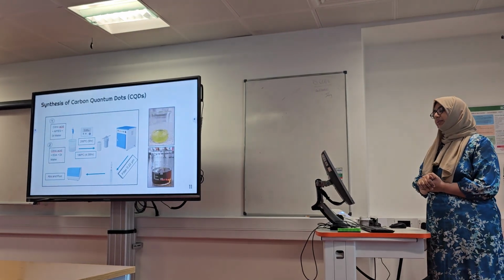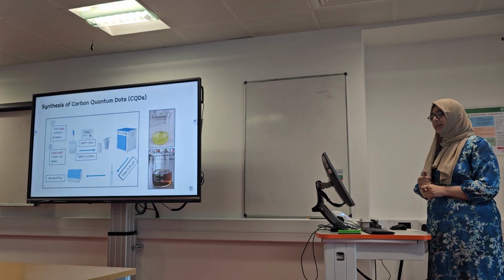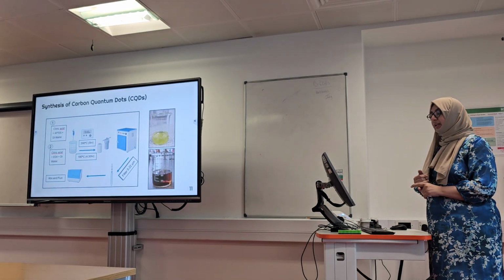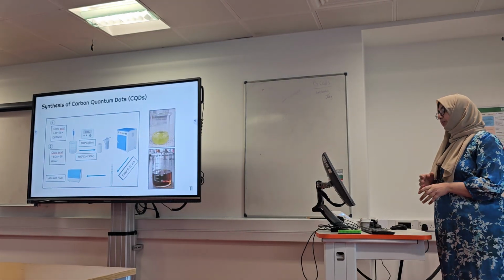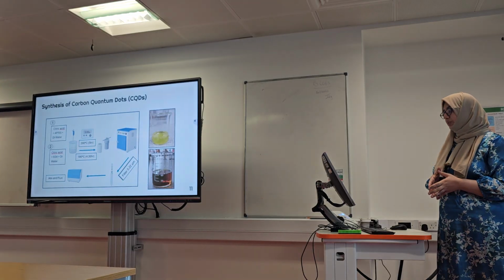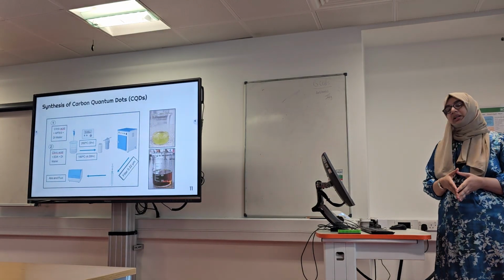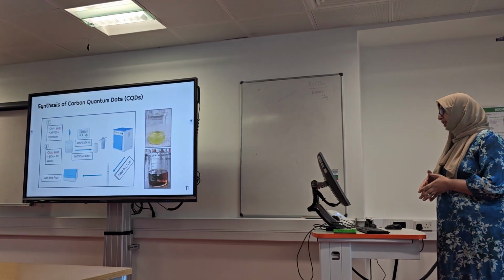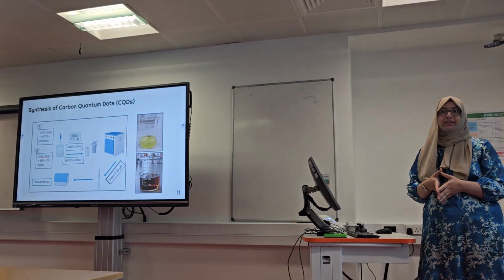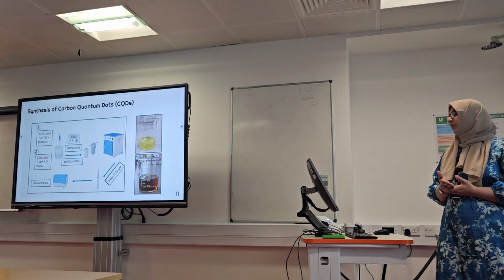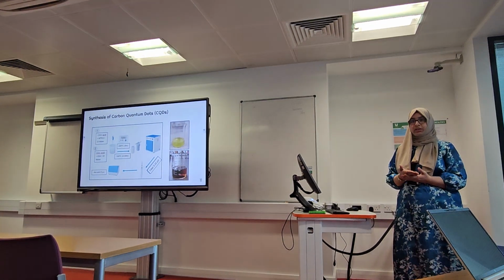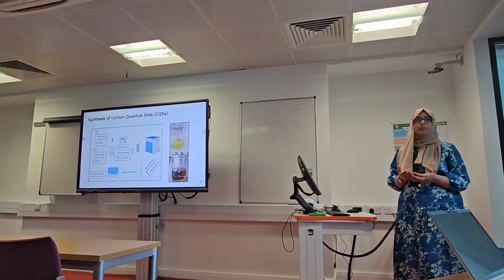The second method was using citric acid plus ethylene diamine and DI water, and the procedure is the same, but the timing I use is 4.5 hours at 180 degrees centigrade. Then the rest of the procedure is the same. Put in the hydrothermal reactor for the mentioned time, then filter the solution, and at the end check the absorbance and the fluorescence.